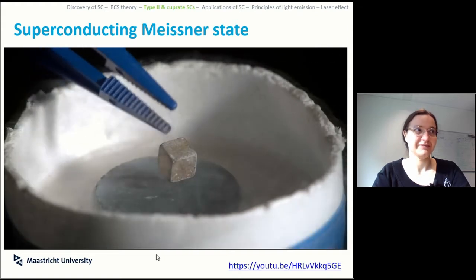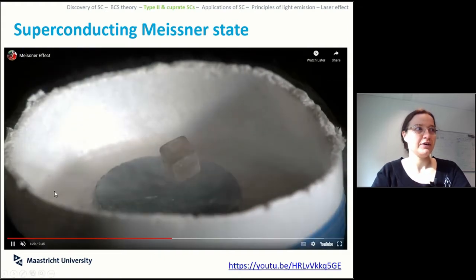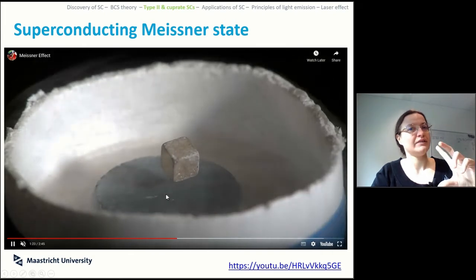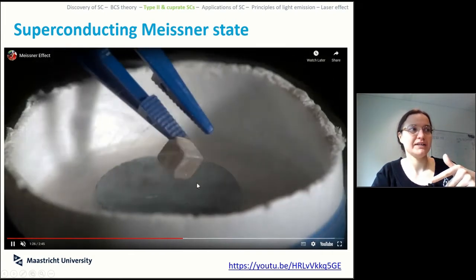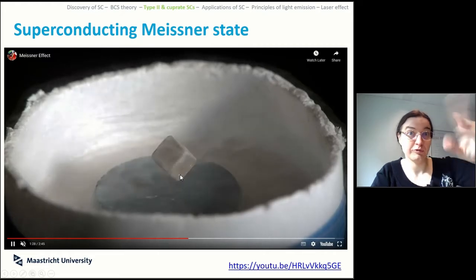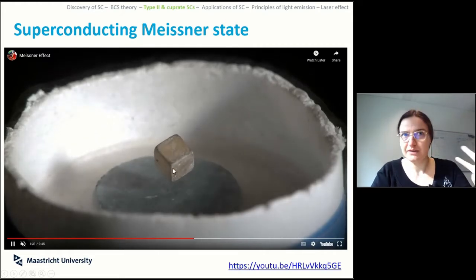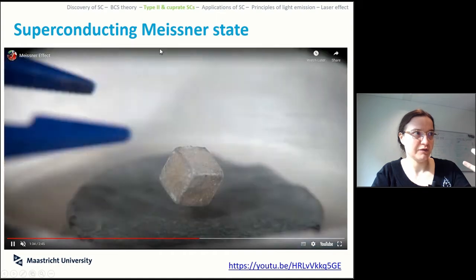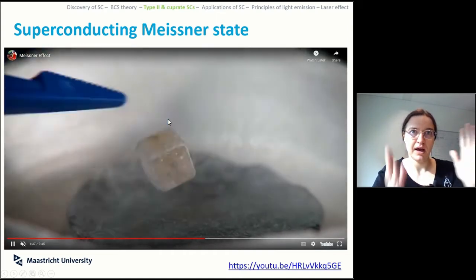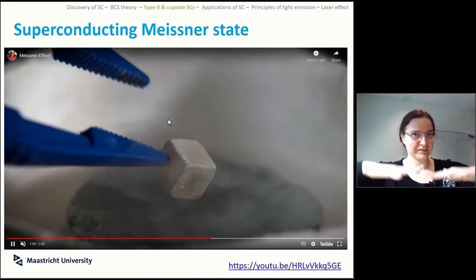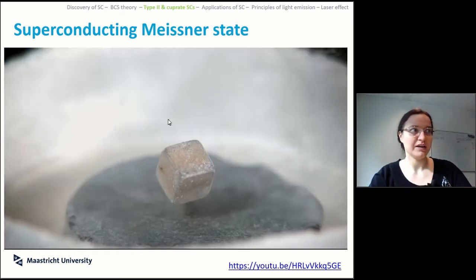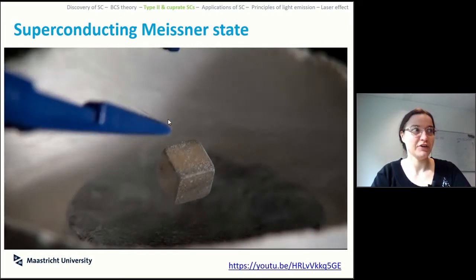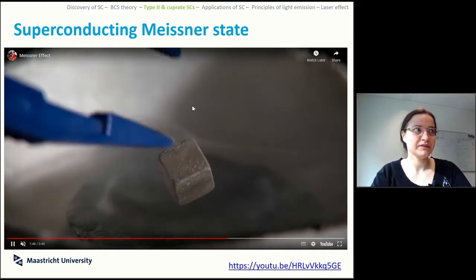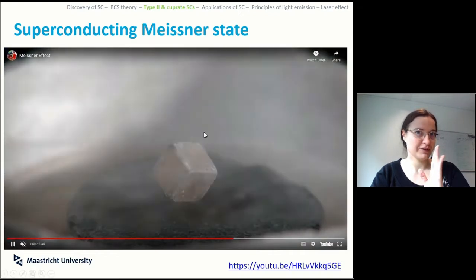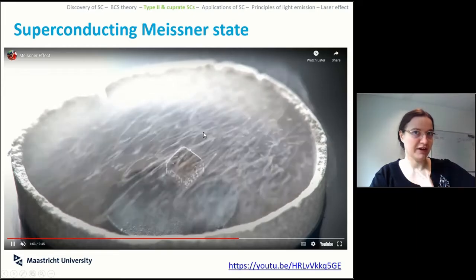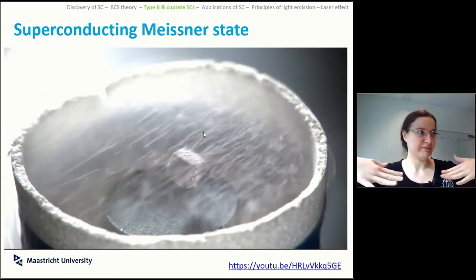So this is the Meissner state. This is sort of done in the reverse fashion, so you are floating a magnet on top of a superconductor rather than doing it the other way around. But this still works, because basically this means that the lines of field that your magnet is trying to impose are being repulsed when it tries to touch the superconductor. And so this thing floats. And you can spin it, you can try to move it, but you can see that it floats in a very specific position, because this is giving the lines of field and everything is being pinned.